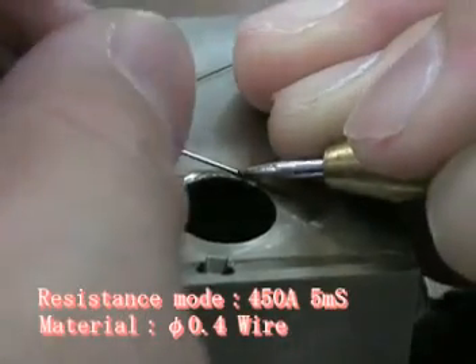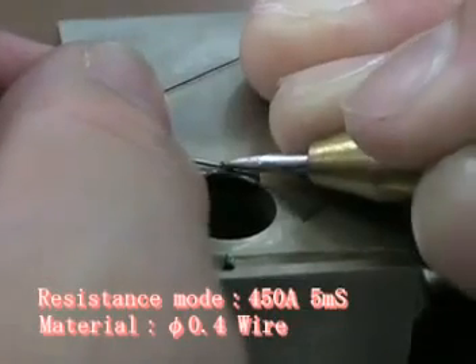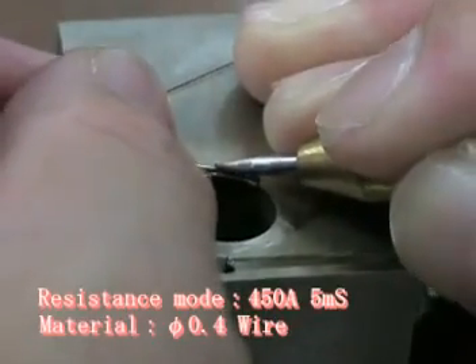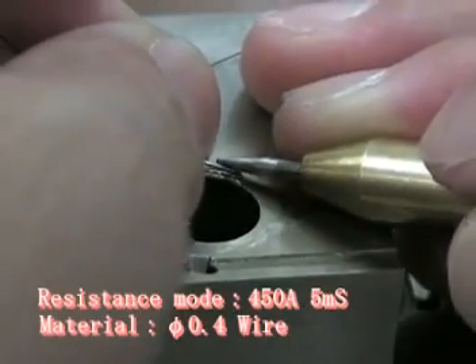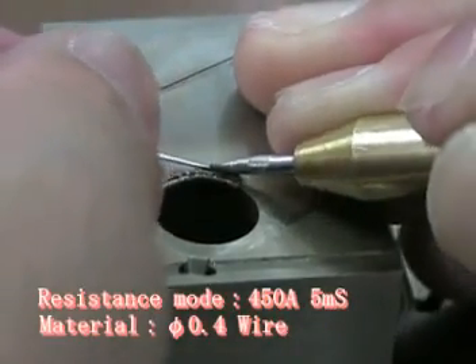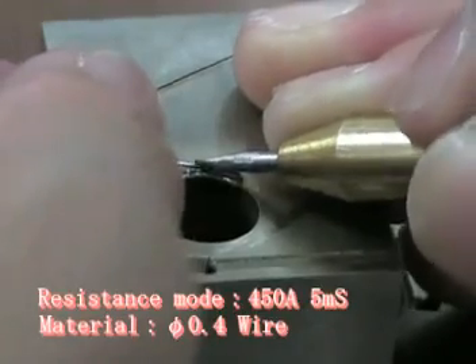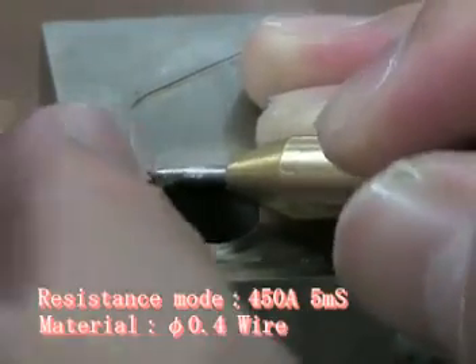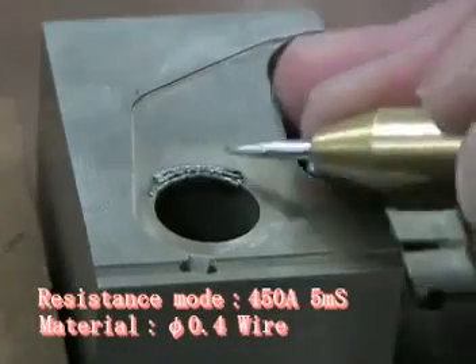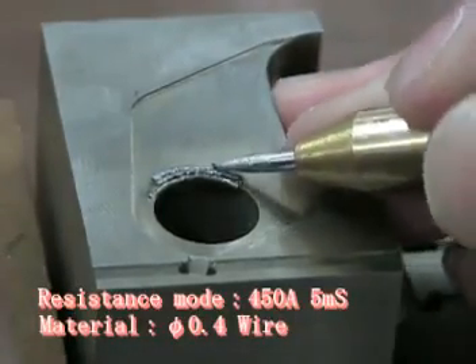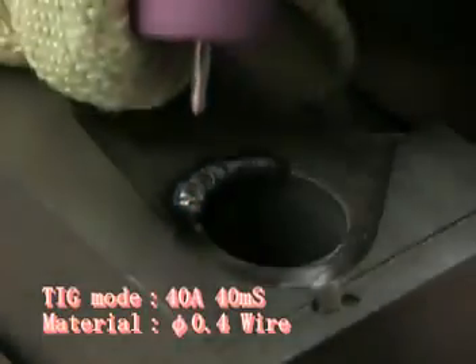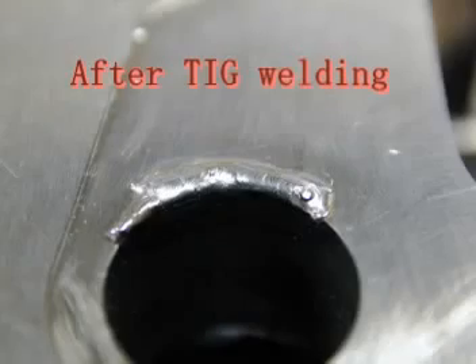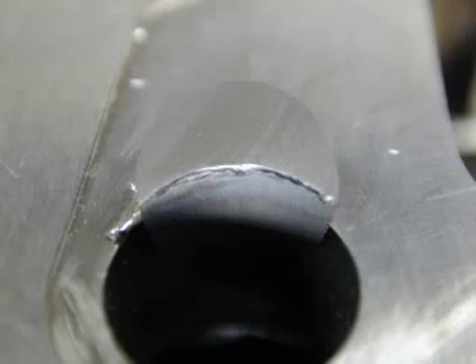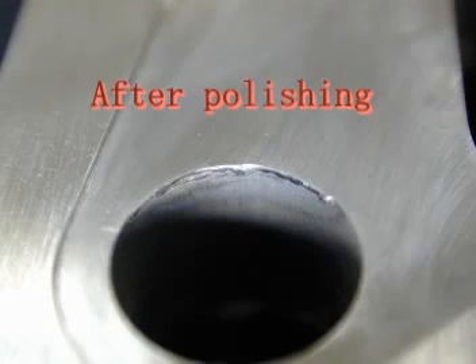Use wire materials to repair scratches remaining on the flat surface. Depending on the size of the scratch, prepare 2 wires. Apply a little extra material than the size of the scratch. When you weld using the TIG welding method, weld in the continuous mode and move the torch slowly. You can see that they are welded firmly and there are no parting lines after grinding.